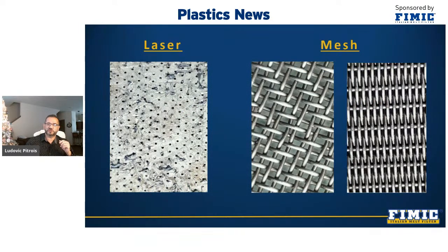In this enlarged picture, you can see the difference between the screens drilled with laser technology and the woven meshes or even Dutch weave mesh type. Those three are classified as 200 micron. We can definitely see on the left, the laser screen picture, the precision, consistency, and uniformity of all its perforation. While on the woven mesh, in the center picture, we see a substantial difference between the opening of the fabric, and the lower variation in the right picture, but it will definitely deform during the process, especially with high pressure, and is of greater cost and certainly remains less uniform than the laser screen.